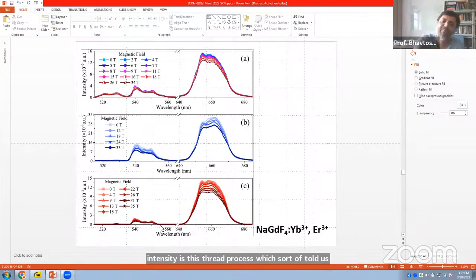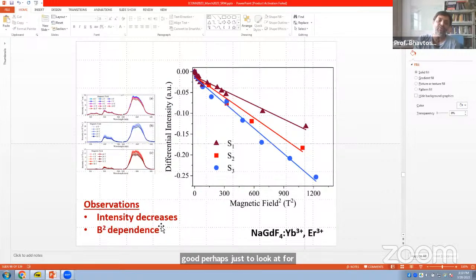So as far as the FRET process is concerned, one could perhaps just look at how the intensity itself is changing with magnetic field. And when you do that, you observe two things. The first thing is that the intensity systematically decreases. These are three different samples which are grown in a similar way, and they are qualitatively similar, but in actual quantitative terms the results are a little different. We can discuss that if you have a question.